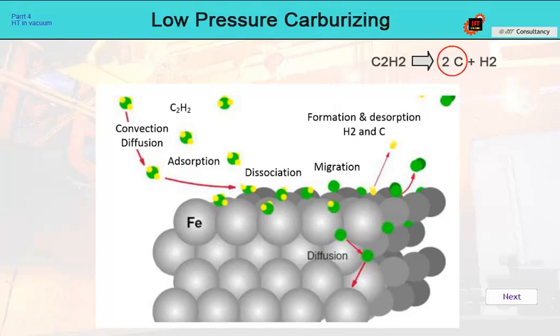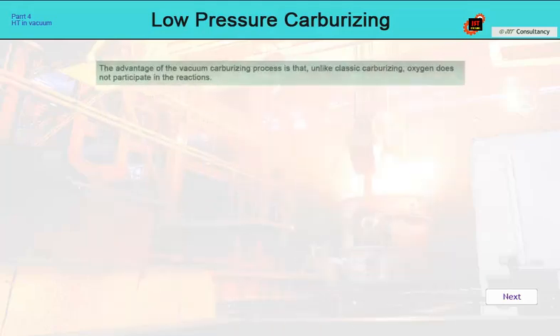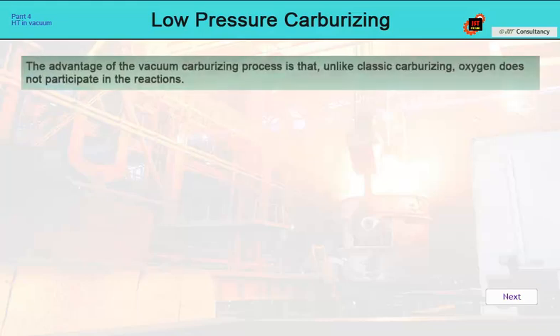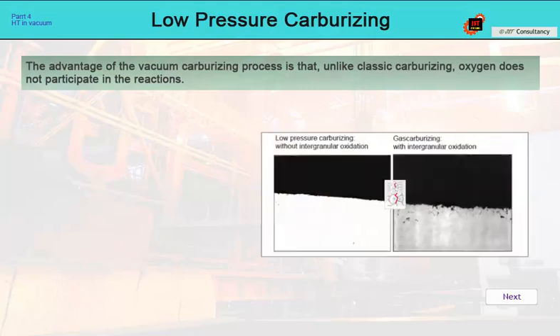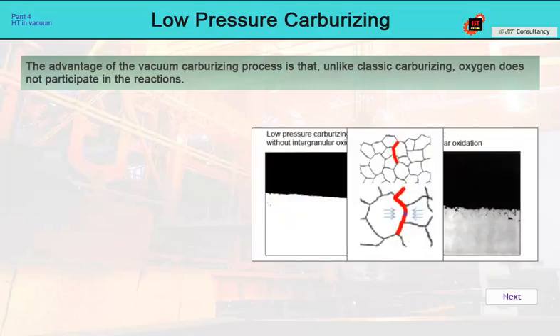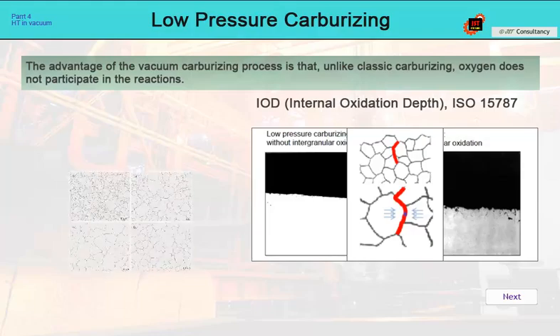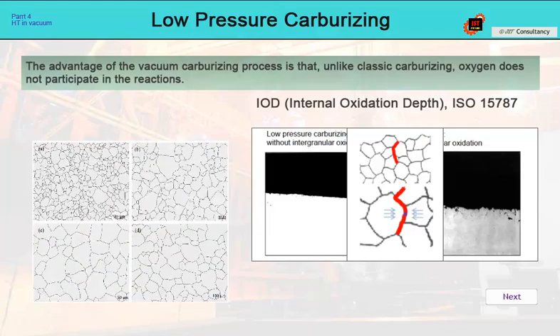by diffusion laws. The advantage of the vacuum carburizing process is that, unlike classic carburizing, oxygen does not participate in the reactions. This is significant in that intercrystalline oxidation does not occur on the surface, measured by the IOD parameter, internal oxidation depth, according to ISO 15787. This reduces the mechanical properties. Another advantage is the fact that we can go to significantly higher carburizing temperatures and thus significantly speed up the process. Given the shorter times, there is no risk of excessively coarsening the austenitic grain.